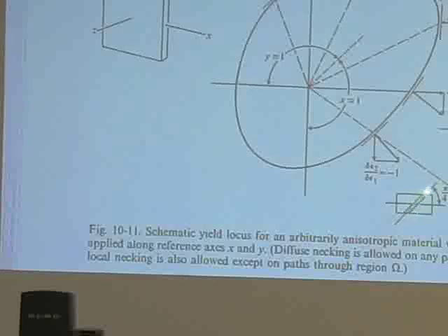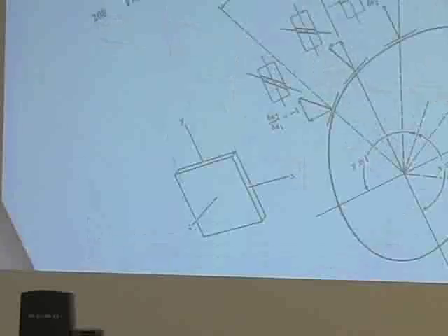You will have changing angles of these localized necks. You cannot have any necking in compression back here, but you can have no local necking in balanced biaxial or on either side of it. So between plane strain and plane strain, you have no local necking. In these regions over here, you can get local necking, and it's all from geometric softening versus work hardening, Considère construction, but we can predict when these necks form.